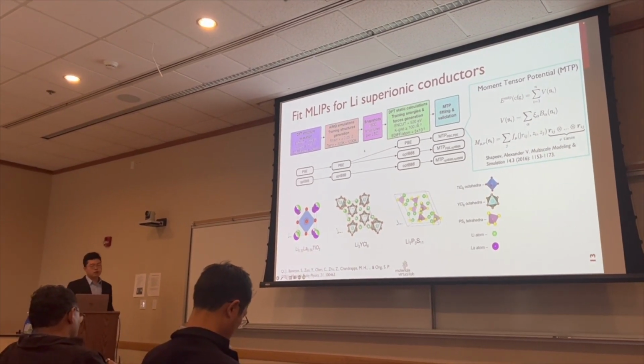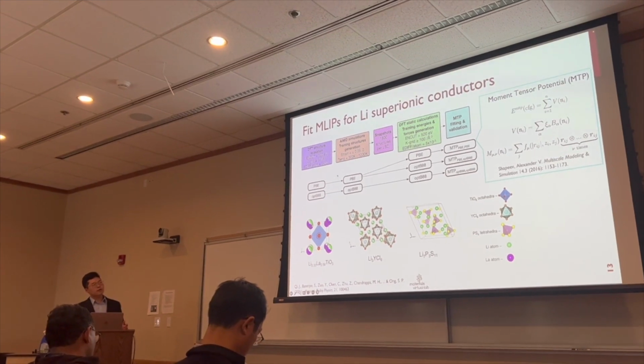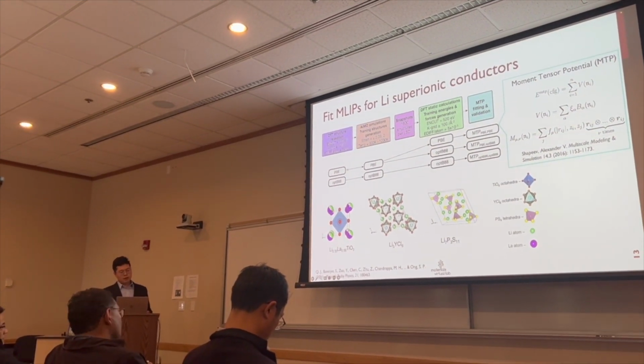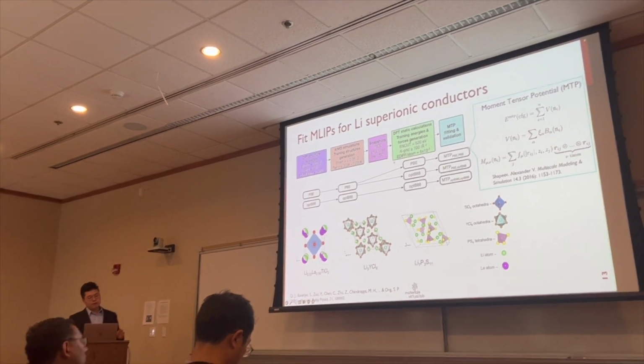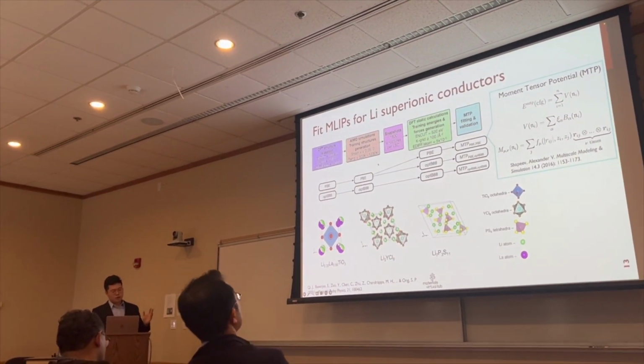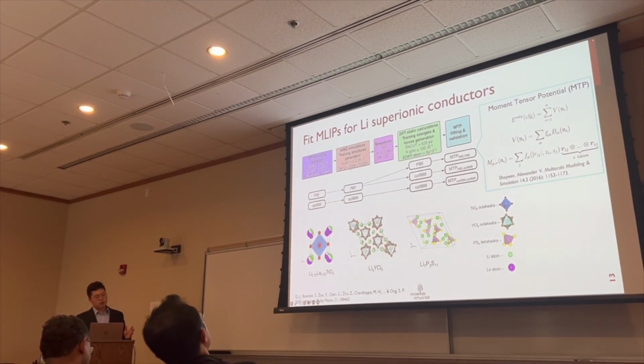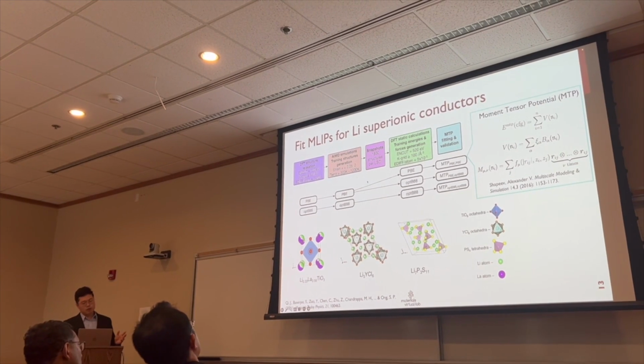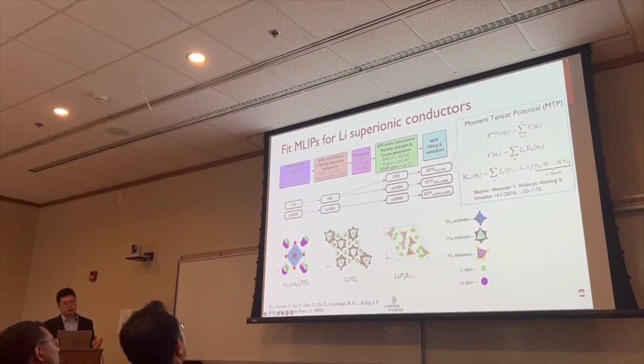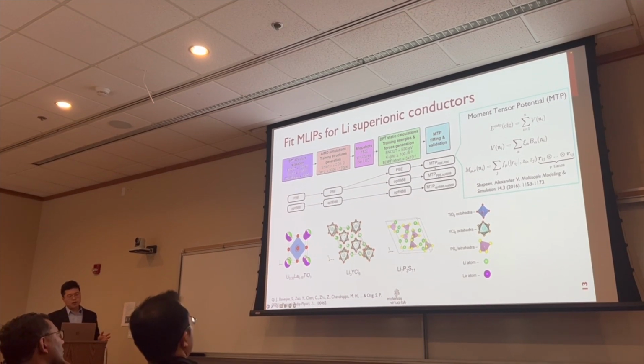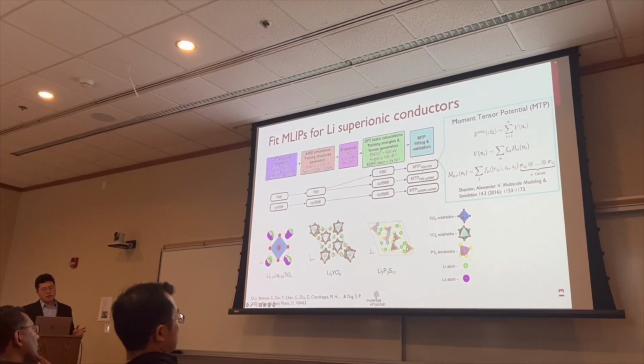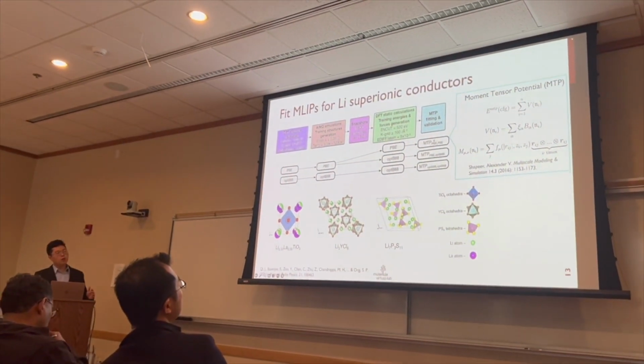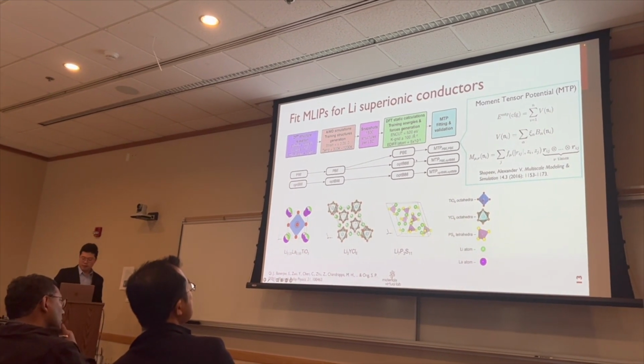In this workflow, I want to highlight that we consider different choices of DFT functional, which are PBE and optB88. The choice of different functionals is in a way that we use these 2 different functionals to perform the AIMD to generate the structures, and we also use different functionals to calculate the energy and forces. So the labeling for this moment tensor potential is such that the functional labeled in front of the comma is the functional we use to generate the structure, and the one after the comma is the one we use to collect the accurate energy and force data.